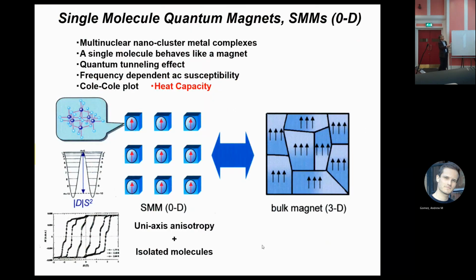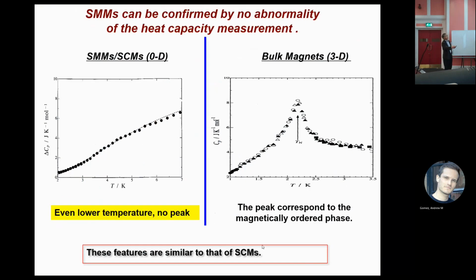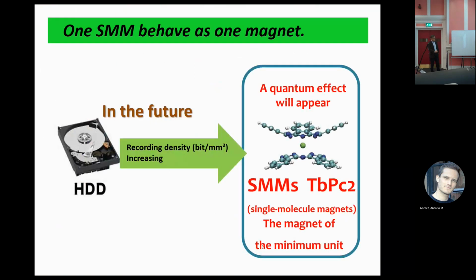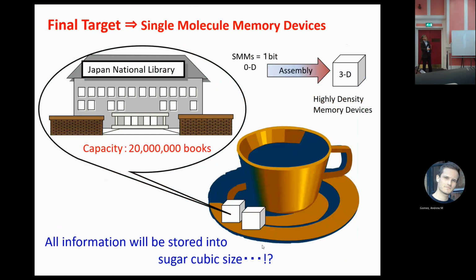And also, heat capacity is a powerful method to detect the ordering. So in the three-dimensional antiferromagnet, at the Neel point, three-dimensional ordering occurs. Then at this Neel point, there are very sharp peaks. This is three-dimensional ordering. However, the single molecule magnet is zero-dimensional, so no peak. So it is perfectly distinguished between a classical magnet and a single molecule magnet. So then, as I said, in order to overcome Moore's limitation, we must use the single molecule magnet such as double-decker terbium. So our final target: the Japan National Library has 20 million books. All information is stored in a sugar-cube-size memory device.